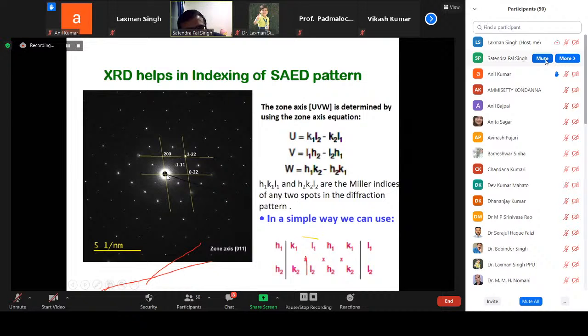Now you can take a printout of this TEM pattern, measure this distance, and calibrate it. For example, say 3 centimeters corresponds to 5 per nanometer. That means 1 by 5 nanometers. Then transform into angstrom and measure how much this distance comes out. Then you can get the d spacing. Once you measure the d spacing, go to the XRD pattern which you have indexed or refined, and find which HKL plane this spacing corresponds to. Based on these two pieces of information, you will be able to accurately index the TEM pattern.